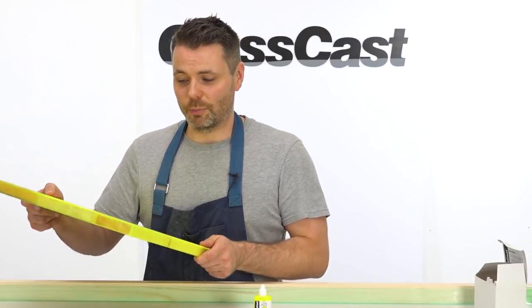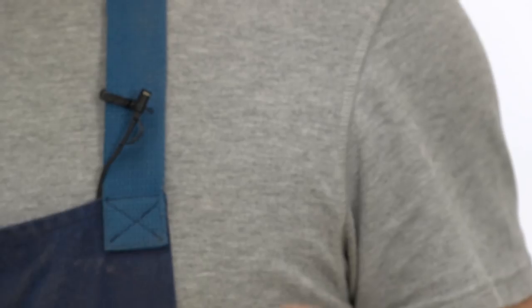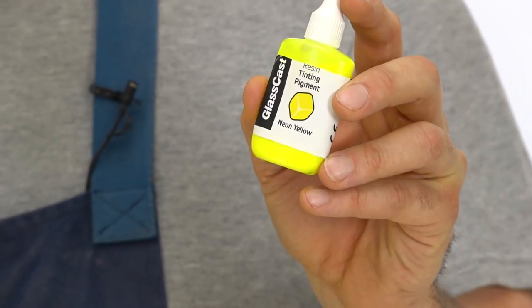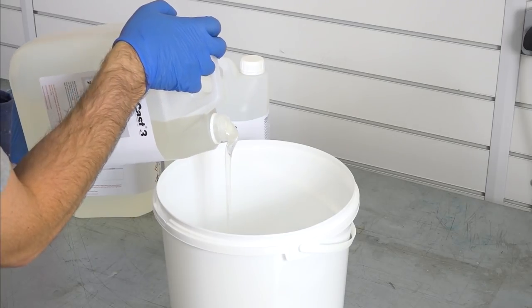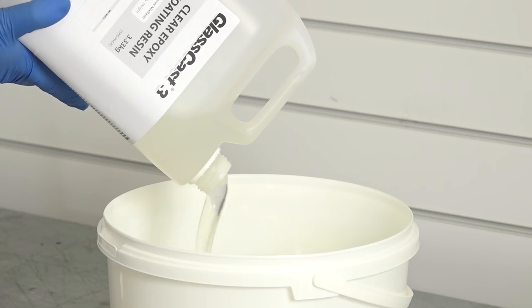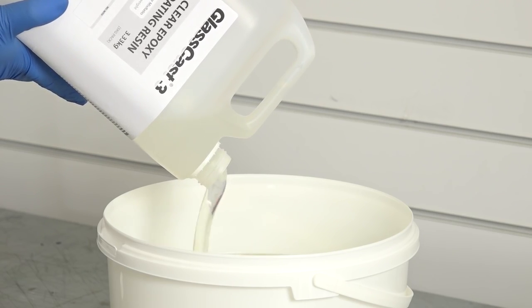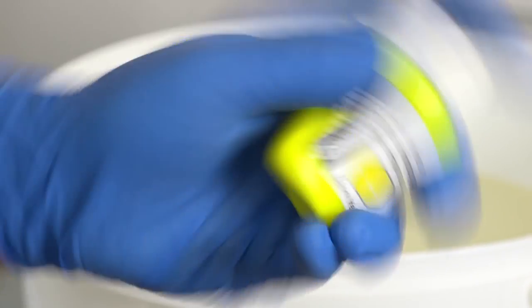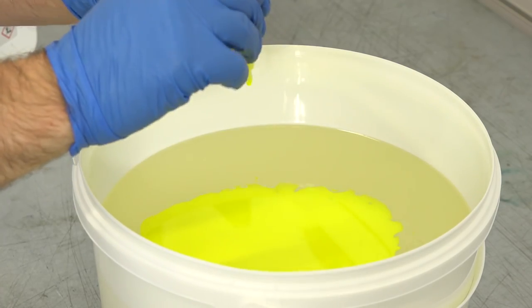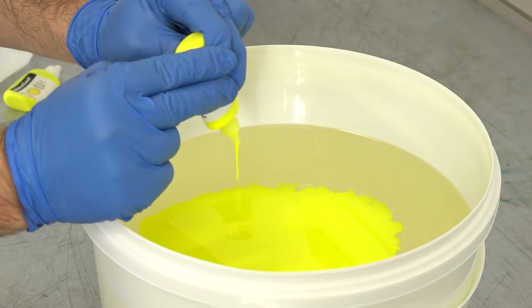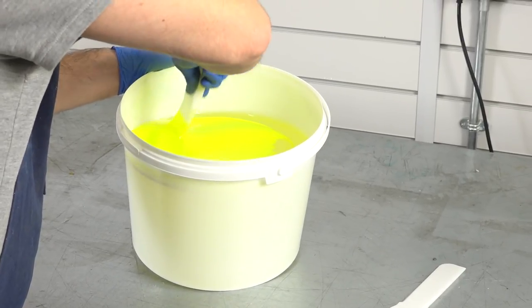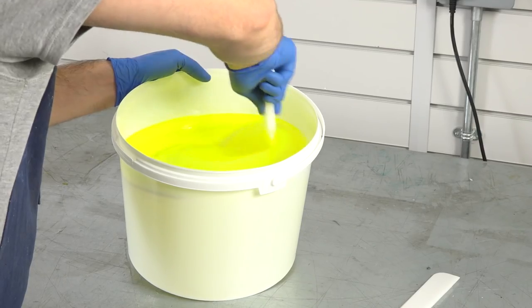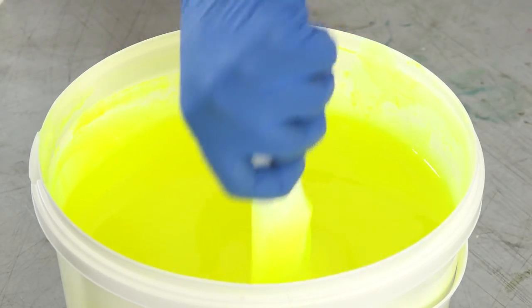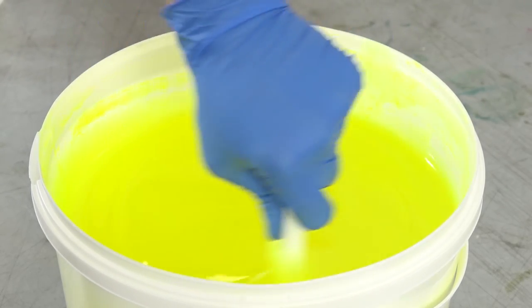To achieve this eye-popping yellow color, I'll be adding this neon yellow GlassCast pigment to the resin. Having done some experimentation beforehand, I found that adding 3.5 grams of pigment per kilogram of resin gives me the vivid but still translucent appearance I want, which means I need about 50 grams of pigment, which is two of these 25ml bottles, to colour all 15 kilograms of the resin. To ensure consistent colour throughout, I'll pigment all of the resin in one go.